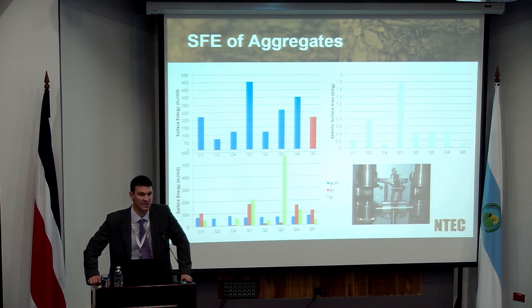We also need to remember that one of the key drivers for adhesion is not just the physicochemical surface energy type adhesion, but also the amount of material interface or surface we have at our disposal. So one of the things you measure indirectly when you're doing your surface energy measurements using dynamic vapor sorption is you do get a measure of the surface-specific area. And obviously, the more surface area an aggregate has, the more area it has to bond with bitumen. And so that needs to be taken into consideration when you look at adhesion. I'm going to show you a few equations in a second.